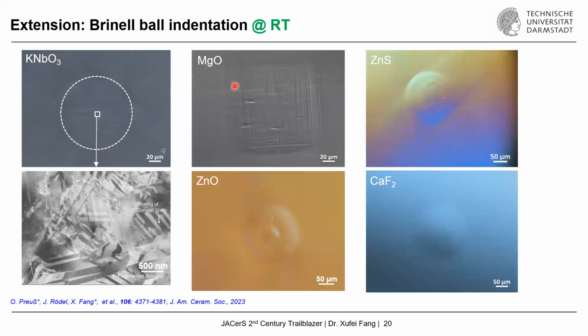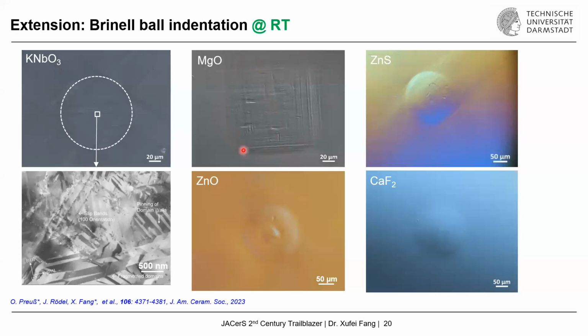So again, we are not satisfied just working on strontium titanate, so we extended the method, also at room temperature, to another material, potassium niobate. As you can see, all the slip traces and dislocations, and magnesium oxide, zinc sulfide, zinc oxide, calcium fluoride, where you can see the slip traces here and here and here inside. Based on the size of the plastic zone and also the load, 1 kilogram or 1.5 kilogram, we can easily compute the mean average shear stress underneath, which is usually hundreds of megapascal. That's a strong indication that for the materials we are presenting here, their dislocations can move rather easily, even at room temperature. So we are also constructing a material database using this fast sampling method.